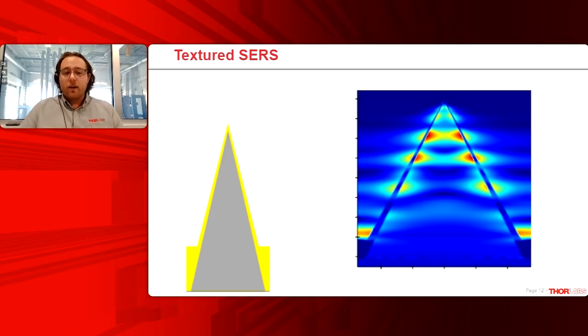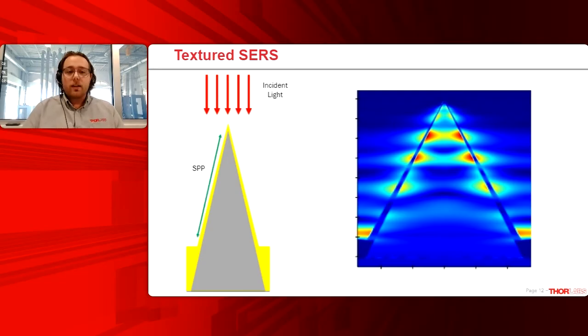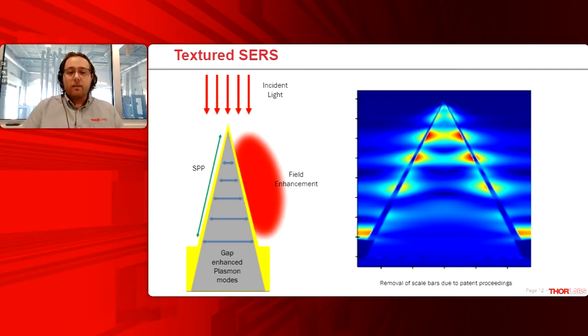Now, the theory of how this may work is that you have some incident light onto your sample, and you can excite some surface plasmon polaritons along the height of the pillar. Now, because these pillars are relatively thin, you can get these gap-enhanced plasmon modes, leading to this broadband absorption of light. And this would allow for this electric field enhancement to be along the entire height of the pillar, or envelop the entire pillar, as opposed to being extremely localized.